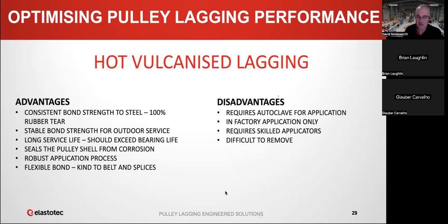David, do you do any additional tests on the ceramic tiles after the autoclave or something like that? This is just because, as I told you, we got this failure maybe 10, 12 years ago, and this makes the client scared when these tiles start to leave the rubber. But the rubber in touch with the pulley, no problem.